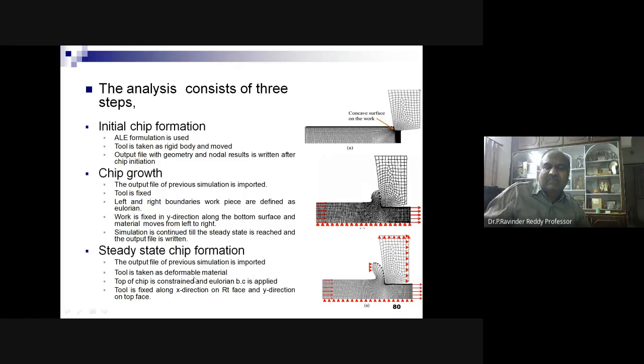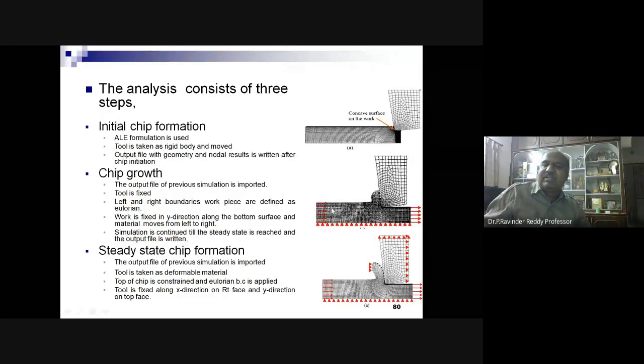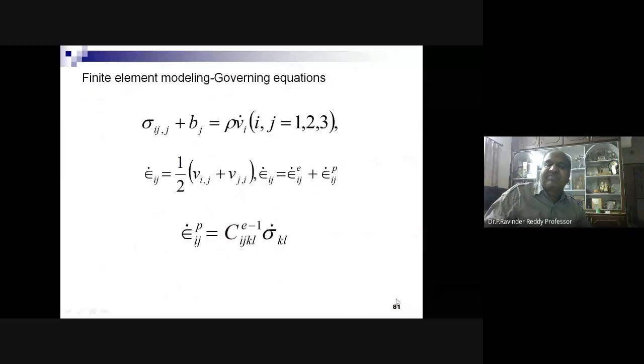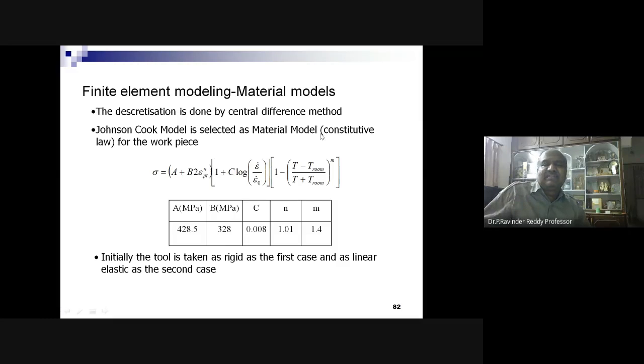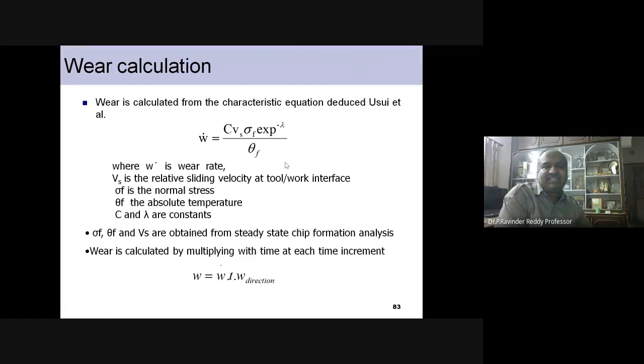Tool is taken as a deformable material. Top of chip is constrained and the Eulerian boundary condition is applied. The tool is fixed along X direction on the right hand side face and Y direction on top face. These are the models corresponding to it. And typically the governing equations used in our constitutive relationships are those, and accordingly the Johnson-Cook model is taken. The constants A, B, C, N and M, the remaining are estimated from the analysis.